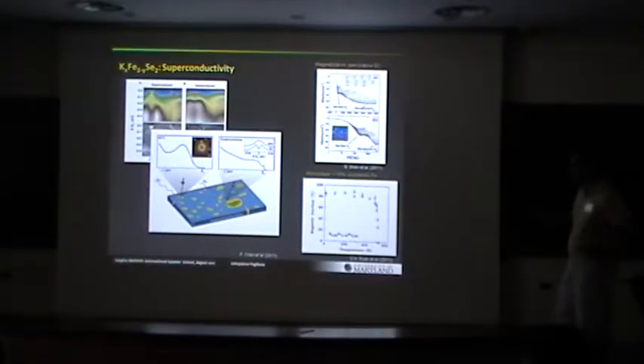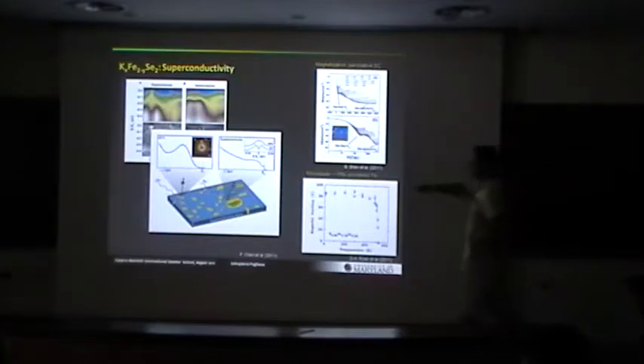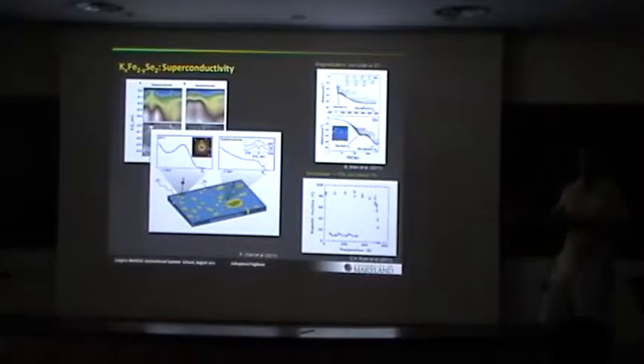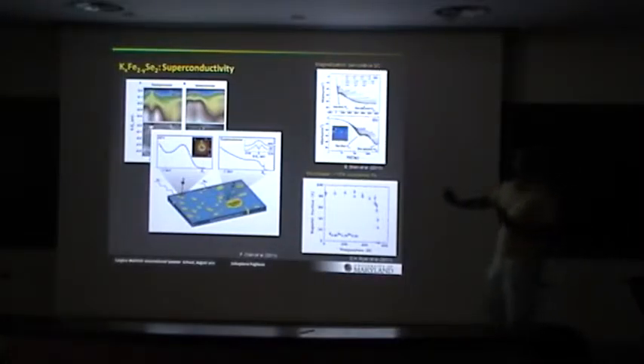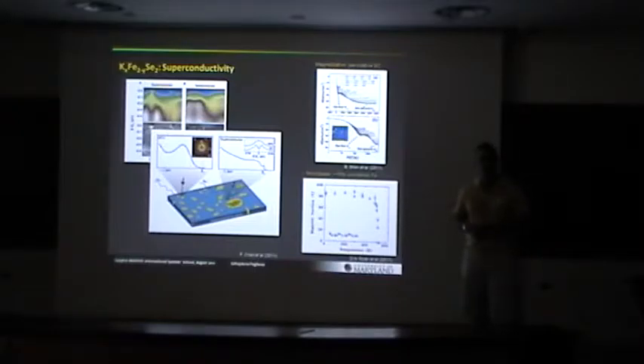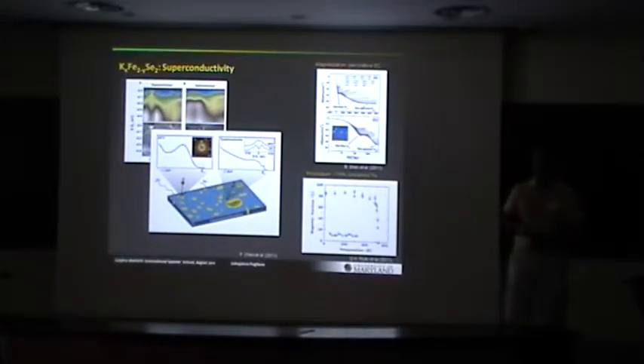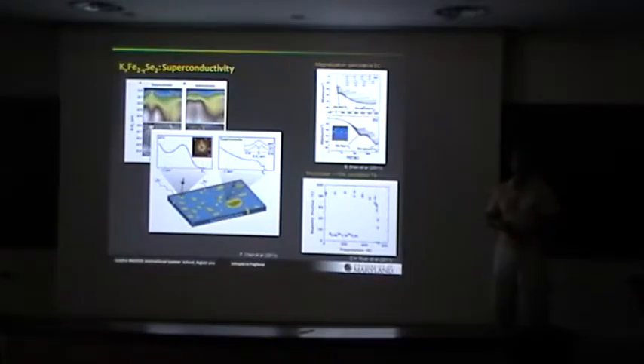Okay, so this is a very interesting result. The Mossbauer shows 15% of the iron is not ordered. So again, this is other evidence for some kind of phase separation. And this is my current understanding as far as we know. This is sort of the latest results. But that's not in the superconducting state, is it? That's all just in the magnetic order state? Yes. So this might resolve the fact that you have a large moment, 500 or 600 Kelvin antiferromagnet and a 30 Kelvin superconductor. Just the remaining stuff.